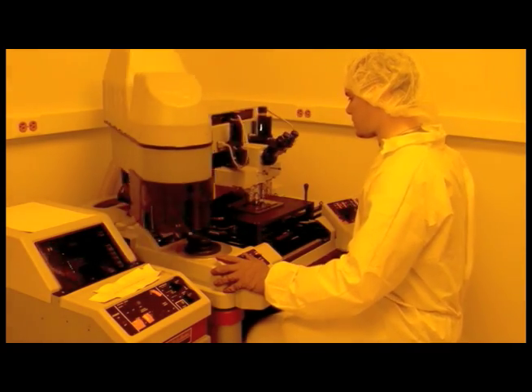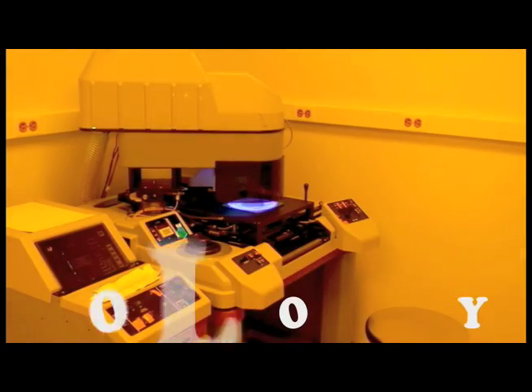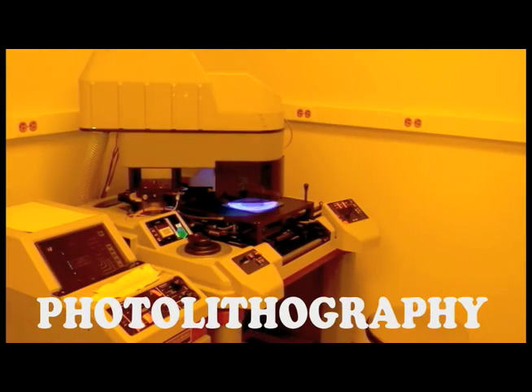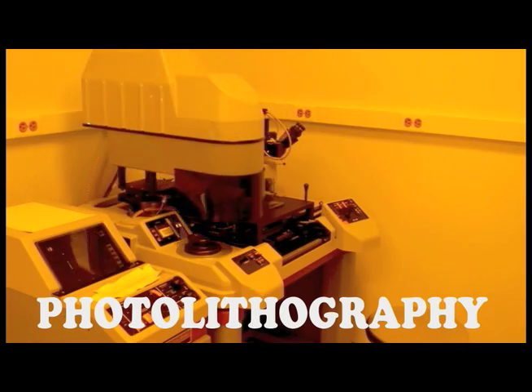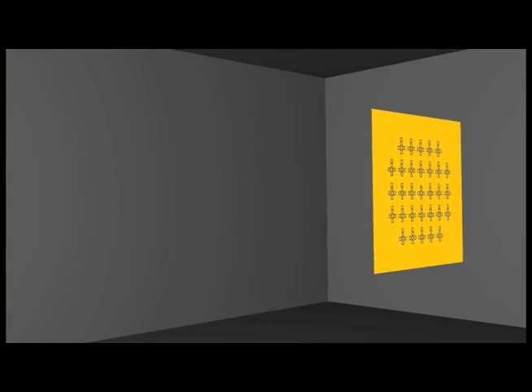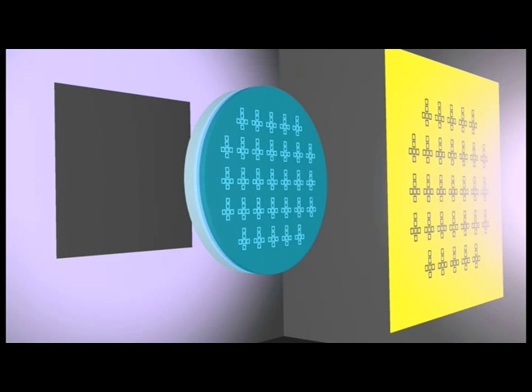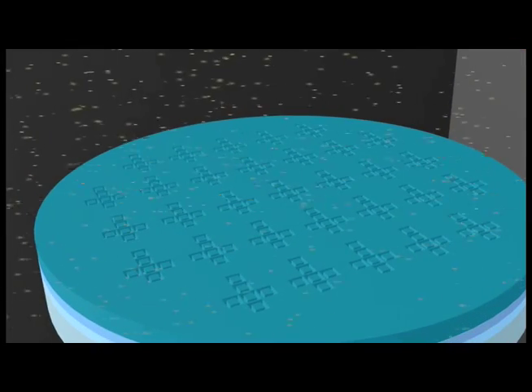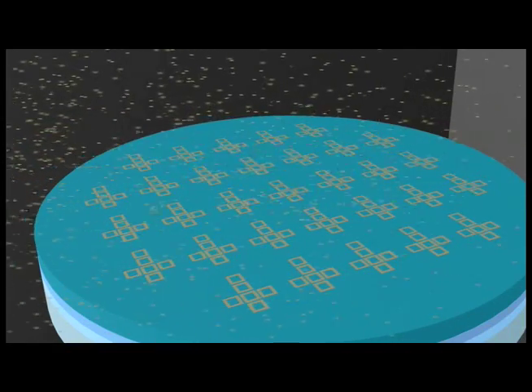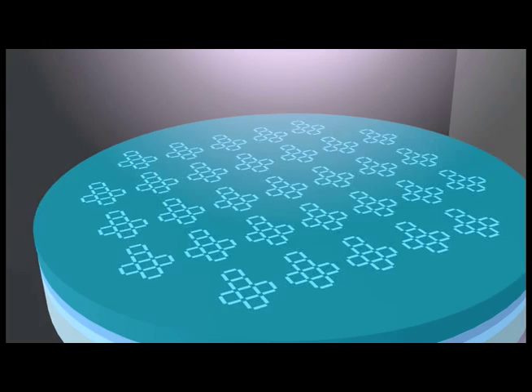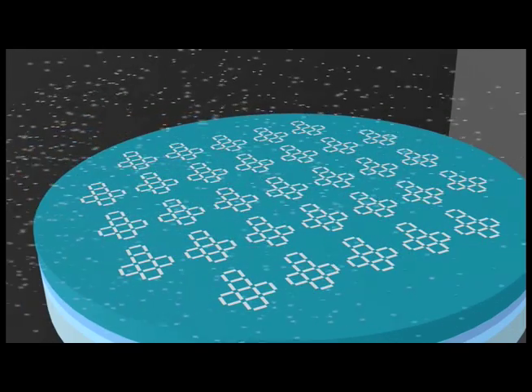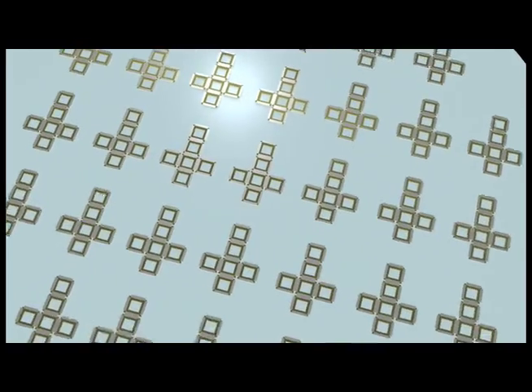In the laboratory, we use a process from the computer chip-making industry called photolithography to make our 2D shapes on a miniature scale. First, a mask is created. It is used to expose a specially prepared silicon wafer and the areas that are hit by the light dissolve away. This leaves a mold behind which is filled with metal, forming the cube faces. This process is repeated, connecting the faces with another metal that functions as the hinges. Once the two-dimensional structures have been prepared,